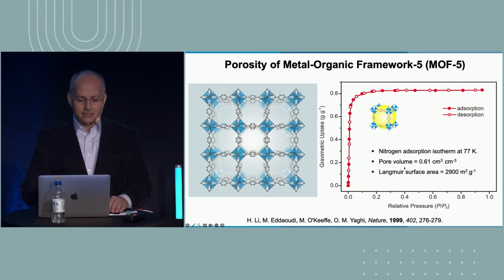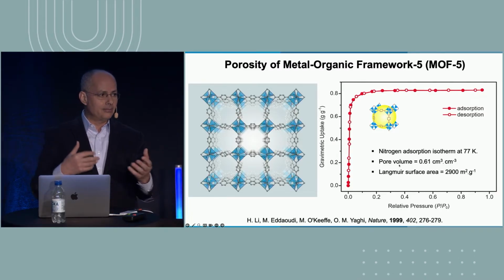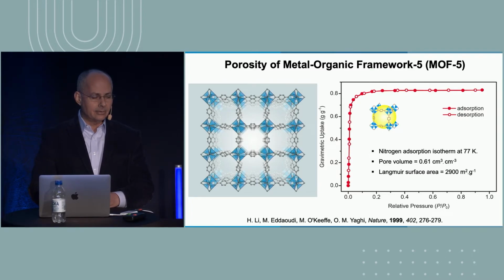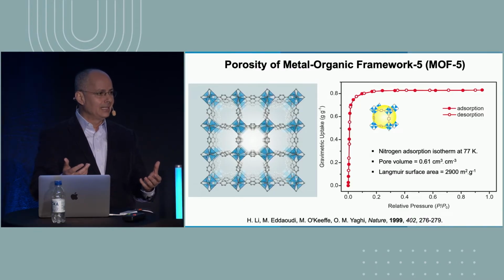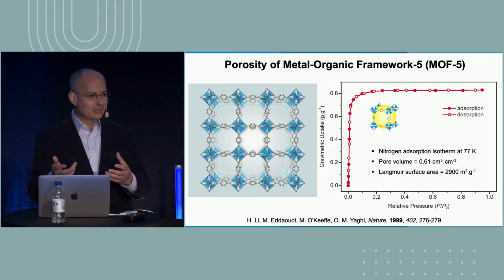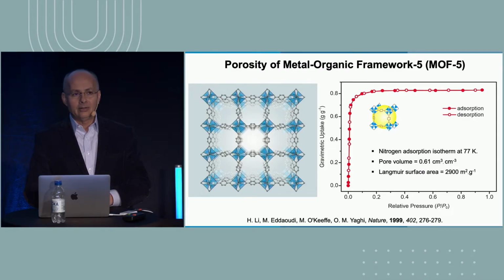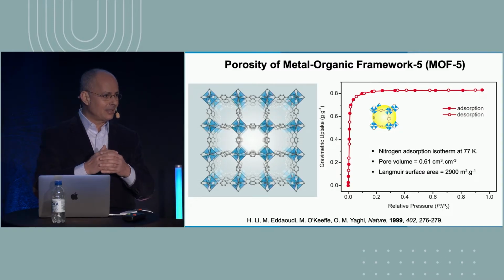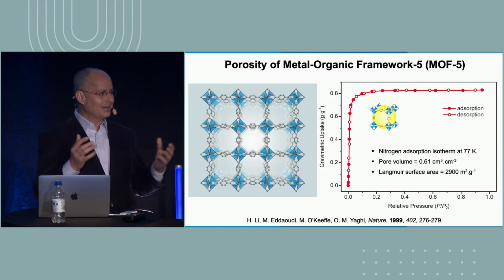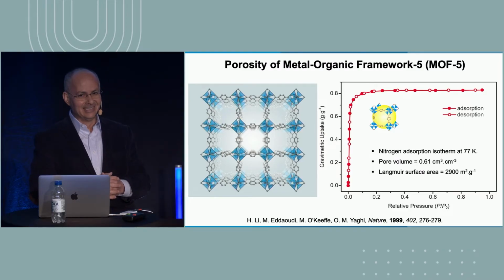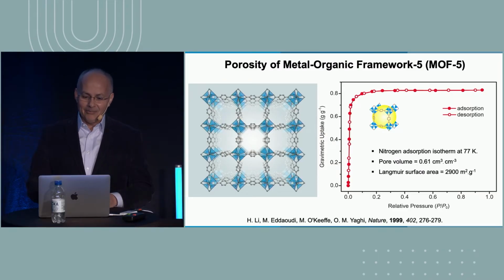The surface area for this material was 2,900 meters squared per gram. That's a number that you derive from this nitrogen isotherm. 2,900 meters squared per gram is 3 times the most porous carbon in those days, or 6 times the most porous zeolite. Okay, this was for a young assistant professor, this was terrifying because you're actually breaking a 1,000-year record of porosity. And so we made sure that we verified this result by sending it to an independent company to measure it.